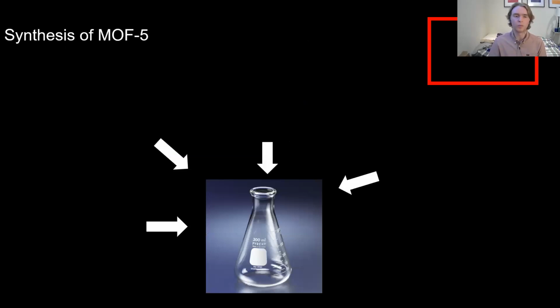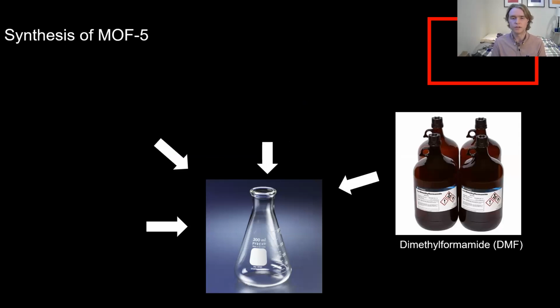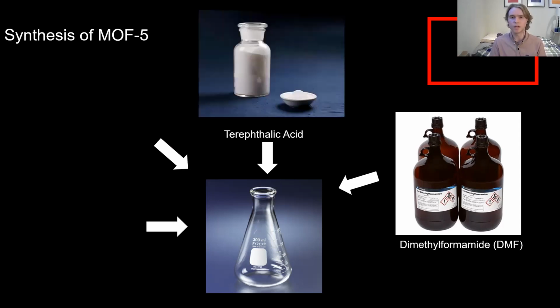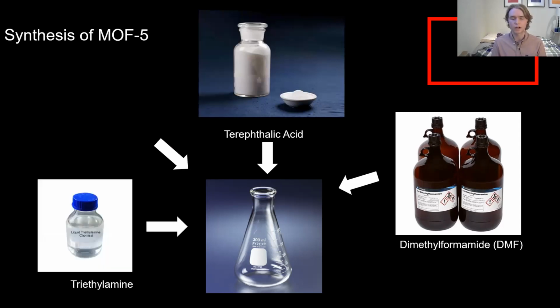So how did I actually go about making this MOF5? Well, starting off, an important thing to note is that all of the synthesis was done in dimethylformamide, or DMF. And this is important to note because all of the spectra that I'll be showing you later is of MOF5 that has some amount of DMF in the pores already, because as I said, when you synthesize a framework, you're always going to end up getting the solvent in the pores. So I made a solution of DMF and terephthalic acid, which is that linker molecule that I was talking about, as well as triethylamine.